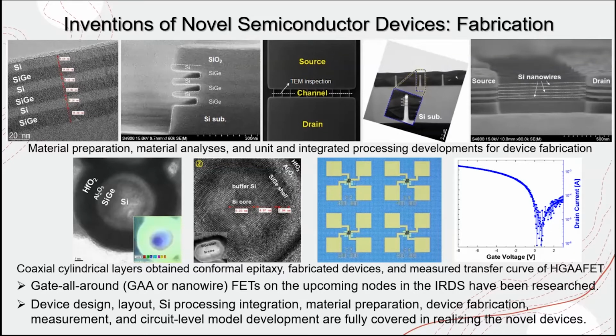So, device fabrication with silicon germanium. This demonstrates one example of the most recent research results of mine. The heterostructure is constructed in the radial direction: silicon core, silicon buffer, silicon germanium shell, and a high-k material as the gate dielectric. And the metal gate was formed to fabricate a horizontal nanowire FET.